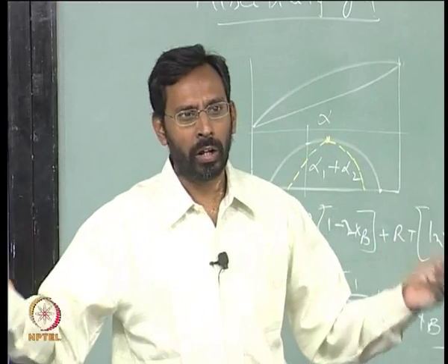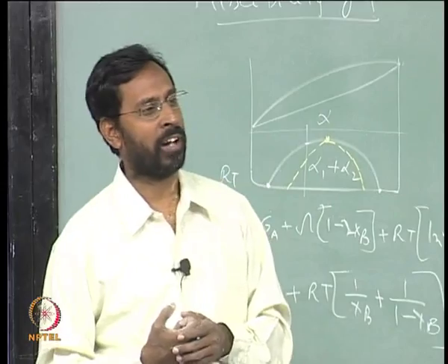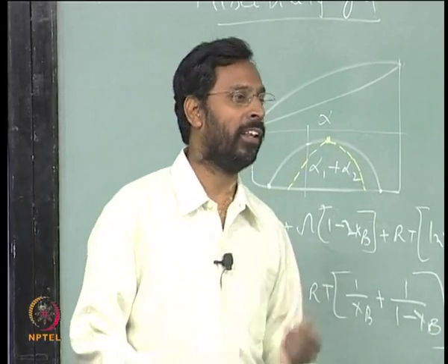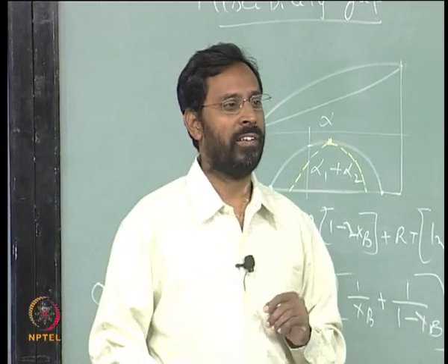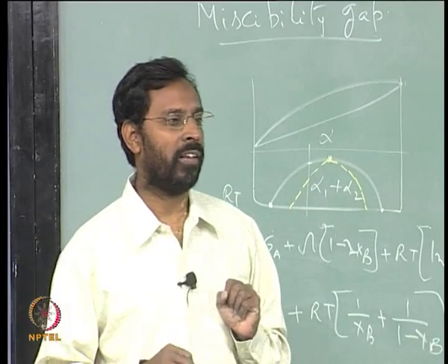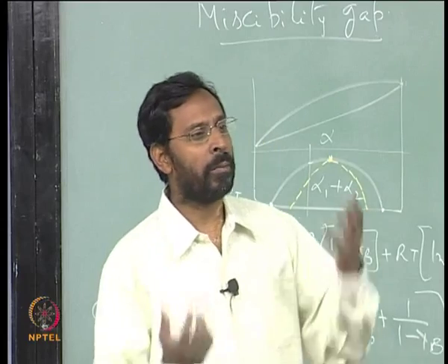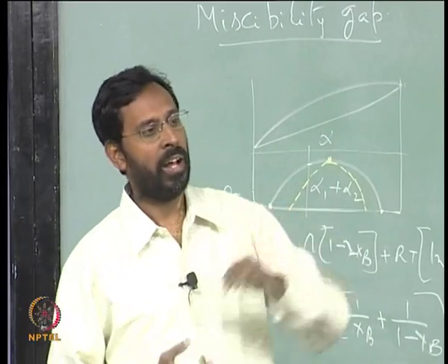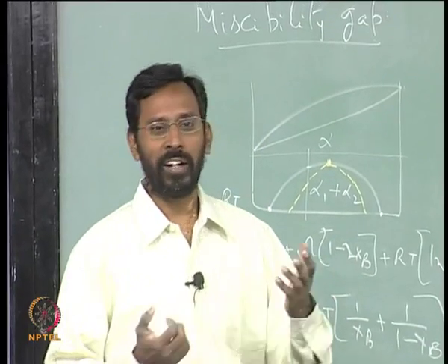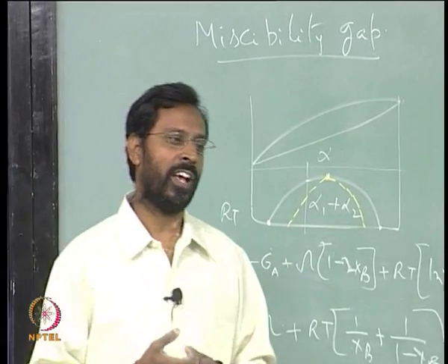And when you look at different elements, for example, Mg2Si is one such example, a size factor compound. You do not see that in every other case. Al2Cu is another, which is to some extent a size factor type of compound. So it looks at aluminum and copper atomic sizes and where they go in. Of course, they are more substitutional, but their atomic sizes are such that aluminum is much bigger when compared to copper. In fact, even for bulk metallic glasses, people are talking in terms of the size factor.